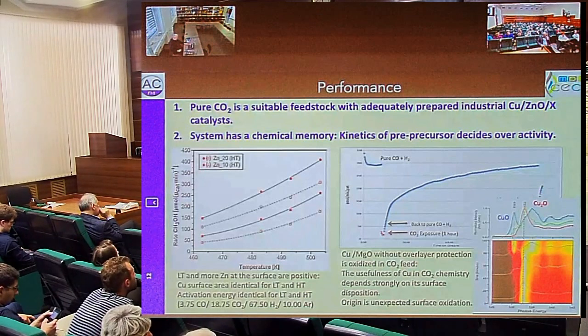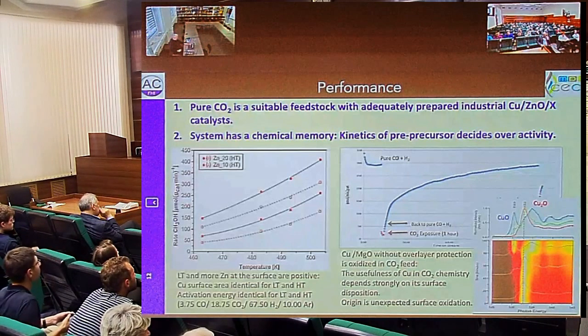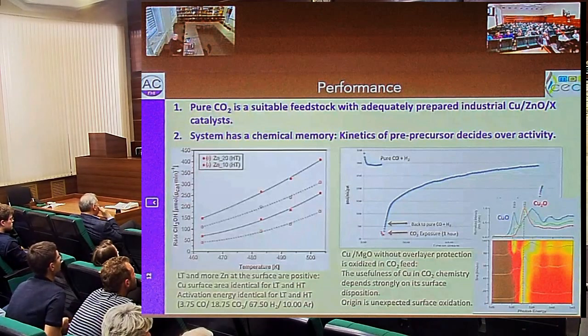That's one of the interesting things, how we do operando spectroscopy. That was not done at high pressure, but it was done at almost atmospheric pressure. I have to mention, if you do this at 0.1 millibar pressure, as many people work, you can only see the oxidized surface. So the chemical potential of hydrogen is critical here. There's a pressure gap. It applies in the area of more than 10 millibar of pressure, and if you're below this pressure, you can't see the partial reduction.